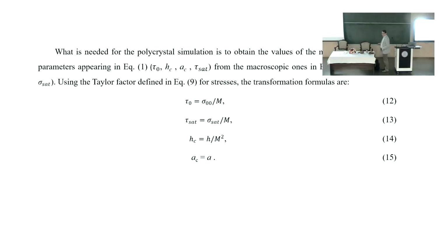So here is the simple transformation. We have these four parameters: sigma 0,0, sigma sat, H, and A, obtained by simple, efficient, fast, and precise fitting. We want to use these values in the polycrystal plasticity code. What we need is tau 0, the strength of the slip systems for dislocation glide—the shear stress which moves the dislocations. It is simply sigma 0,0 divided by m, where m is the Taylor factor. Here we only use the Taylor factor for stress. The saturation value is also transformed from the macroscopic into the microscopic one by the m division.